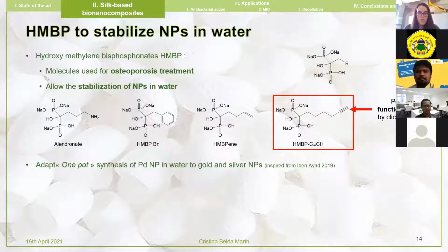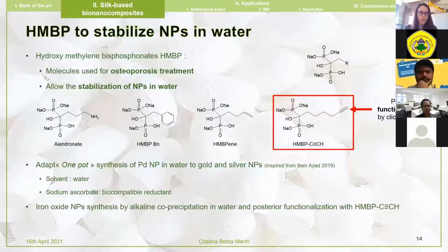So the idea is to adapt the syntheses that we have developed in the laboratory for palladium nanoparticles to gold and silver nanoparticles. What's important about this synthesis is that it's done in only one step, within water as a solvent, and using sodium ascorbate as a reductant for those metals. The third type of nanoparticle that we have chosen to use within this study is iron oxide nanoparticles, which were synthesized by alkaline co-precipitation, which is the standard manner, and then functionalized with our molecule on the surface. These three types of nanoparticles, gold, silver, and iron oxide, are already used in the biomedical field, and that's why we have chosen them.